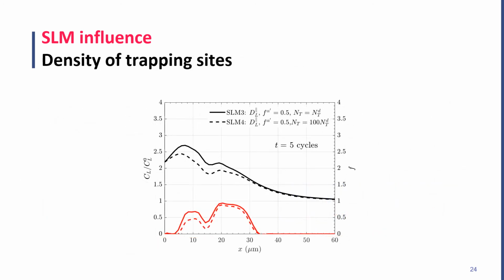Here we analyze the effect of a hypothetical trapping multiplication by a factor of 100. This could be produced, for example, by an excessive distortion during rapid cooling in SLM. And here we plot hydrogen distributions after only 5 cycles. We can see that the higher the amount of traps, the lower the available lattice hydrogen, and so the lower the hydride volume fraction. However, for longer times this effect is weak, and all of these trapping processes also depend on the binding energy of traps.